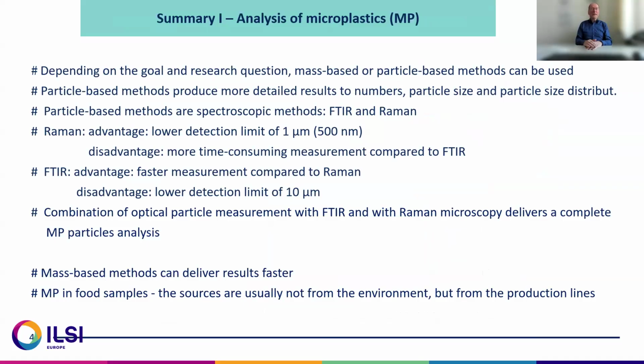The advantage of Raman is the lower detection limit, down to 500 nanometers. The disadvantage is the time-consuming measurement. What is the advantage of FTIR? You have a faster measurement, but the disadvantage is the higher detection limit of 10 microns.